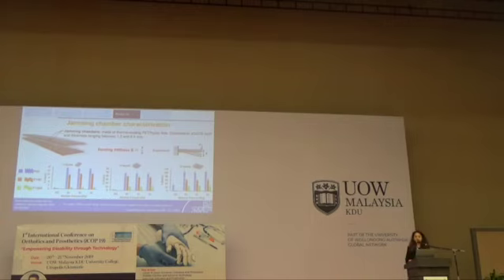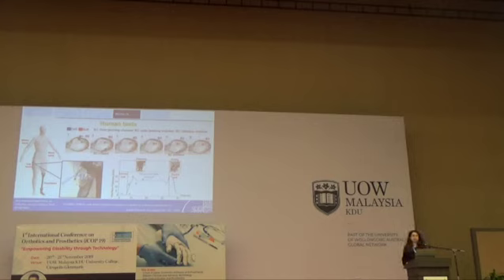To evaluate the performance of the jamming solution, we carried out several bending tests to evaluate the stiffness of the chambers by changing the numbers and the type of the material used for the sheet. And the experimental result showed that the best solution is a jamming chamber with 15 layers of sandpaper P180. Then a wearable band was manufactured, and it was wrapped around the limb of a healthy voluntary subject to confirm the applicability of the system.